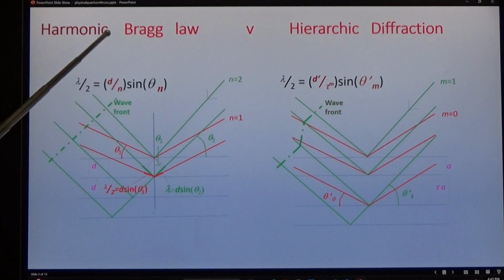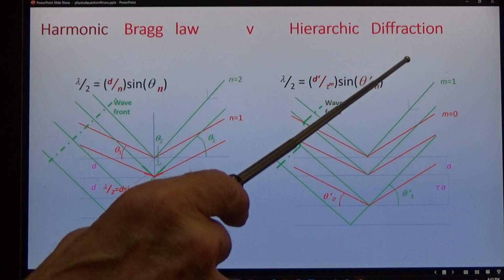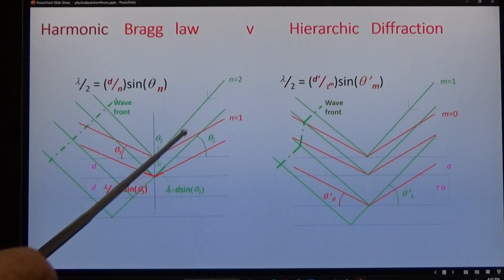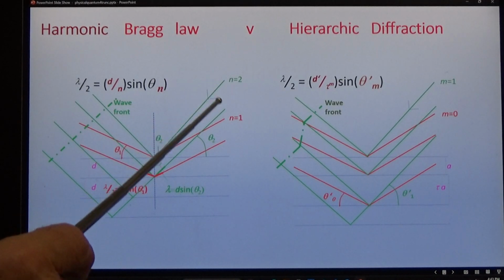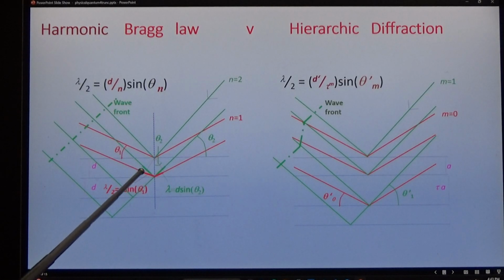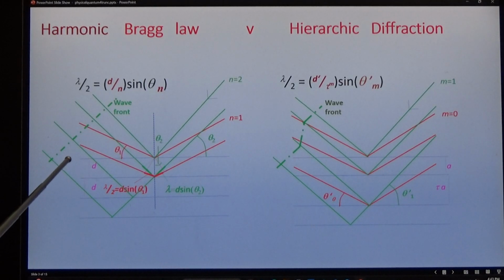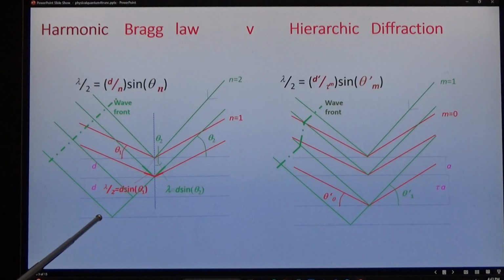the diffraction mechanism for the crystal and the quasi-crystal. Look at the red rays. The difference in path length is lambda. And in second order, the green rays, 2 lambda. And the wavefront is planar coherent. The interplanar spacings in the crystal are unique for any particular diffraction beam.